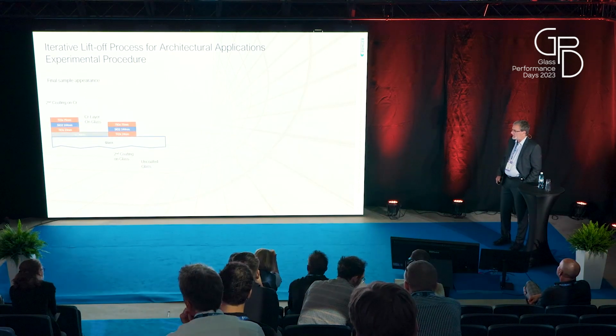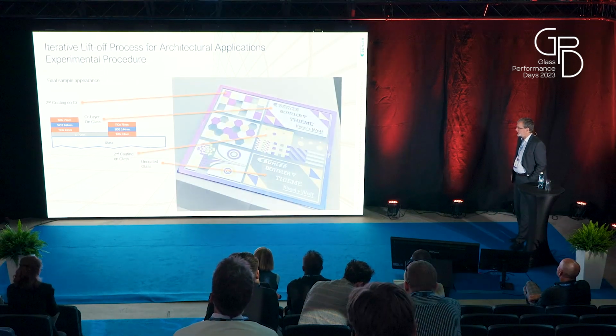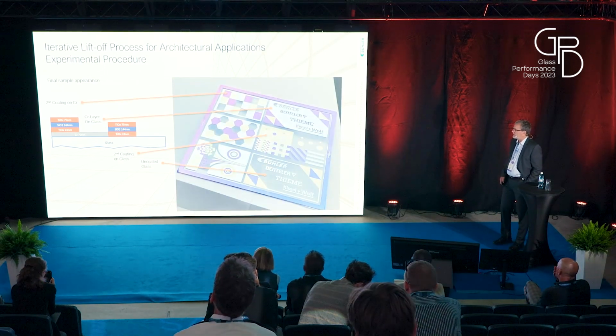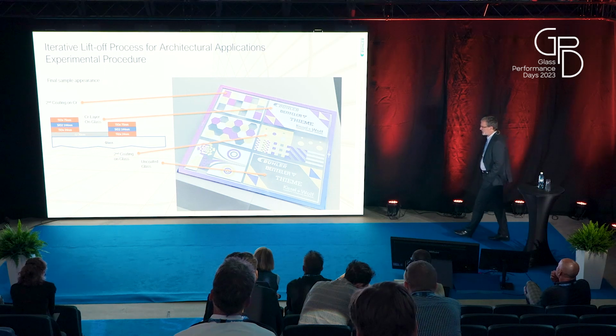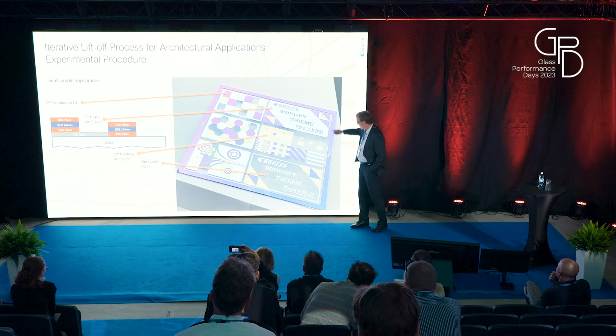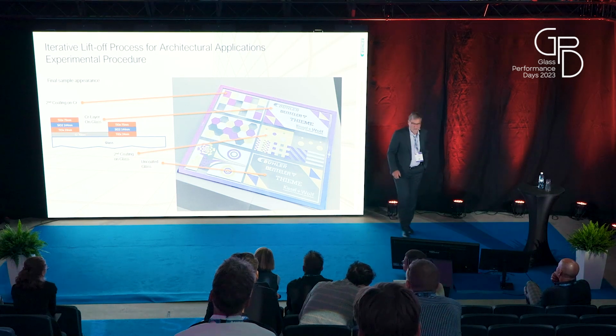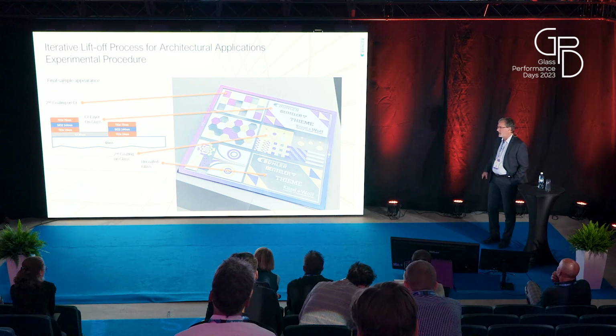Again here, so this was our stack, and this is the final sample. So you see this dielectric coating on chrome. This gives this reddish and bluish appearance. And this is not a non-uniformity that you see, the same layer here reddish and here bluish. It's just a very strong angle dependency of the coating. This was not designed for very stable angle dependency.